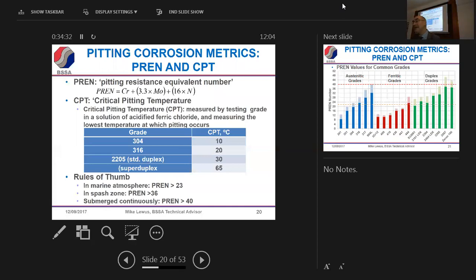And when it comes to something like pitting and crevice corrosion, we can quite confidently rely on a couple of metrics. One is the pitting resistance equivalent number, which I'm guessing some people have heard of, if not everyone. There's a few nods, and it's an empirical formula that bases the level of pitting resistance you get from the grade simply on a function of the amount of chromium plus 3.3 times molybdenum and what else is up there, plus 16 times nitrogen. So you already see there's a way of ranking a stainless steel grade in terms of how resistant to pitting and crevice corrosion it's going to be.